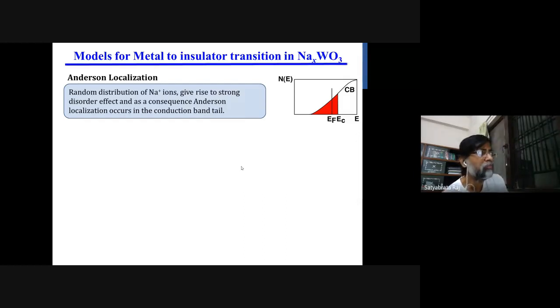So if you dope sodium, sodium can go inside the crystal randomly, and this random distribution of sodium plus ions gives rise to a strong disorder effect. As a consequence, Anderson localization occurs in the conduction band tail, and all these states are localized, and you have a critical edge of this strong localization. If your EF lies below your critical edge, the system is insulating. If you put more and more sodium, your EF will move upward, and as soon as it crosses your critical edge, it will become metallic.